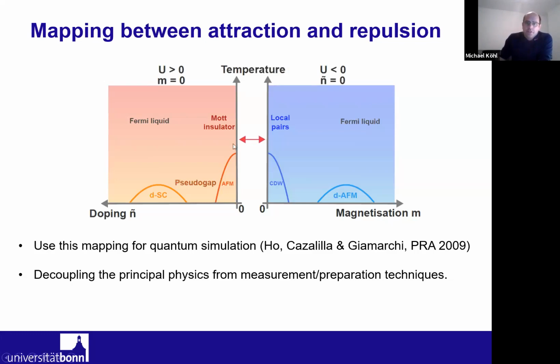And so, for example, the Mott insulator, as I showed you, maps to the local pairs. The antiferromagnet maps to the charge density wave of the doublons. The D-wave superconductor that is somewhere expected to be down here maps onto a D-wave antiferromagnetic phase and so on. And this mapping that is exact under this particle hole transformation, of course, provides you with a fantastic opportunity that you can possibly identify certain phases better in momentum space or in real space, and this mapping gives you the opportunity to choose whatever detection method you have available to detect this or that phase.